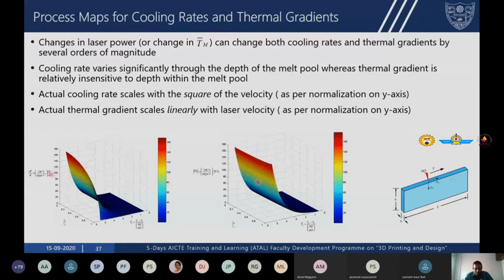Now, here what I'm actually showing is we are plotting dimensionless cooling rate as a function of a relative depth within the melt pool. So 0 is the surface of the melt pool, 1 is the bottom of the melt pool, and you are plotting as a function of Tm bar. We have already defined Tm bar in the previous slides. Now, moving along this axis implies you are changing the Tm bar, which implies you are changing the laser power at constant wall thickness. So this map shows that both these maps for cooling rate and for thermal gradient, they show that both cooling rate and thermal gradient vary with changes in process parameters such as power or velocity.